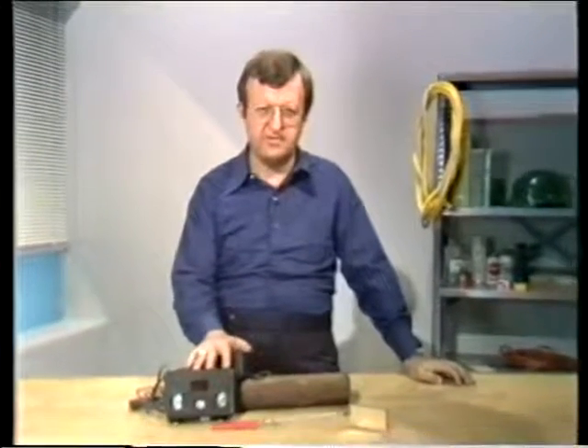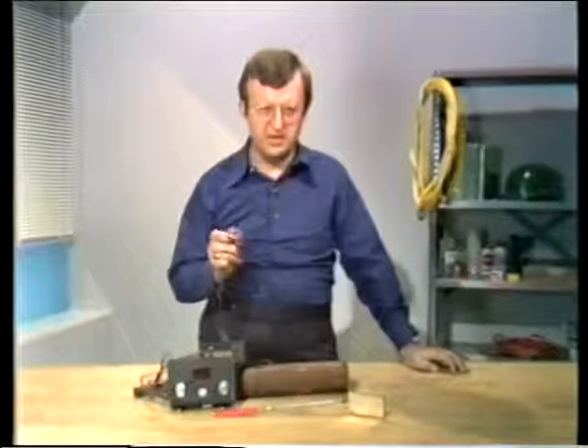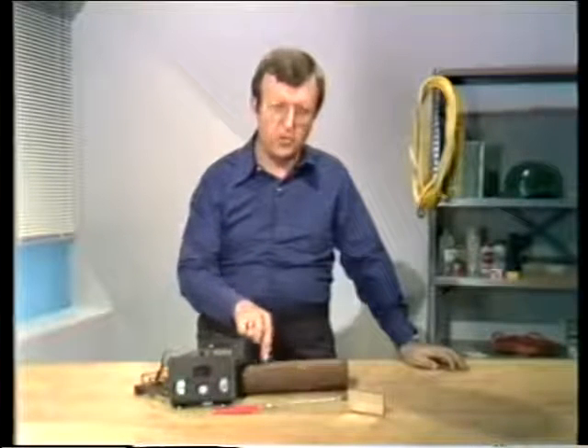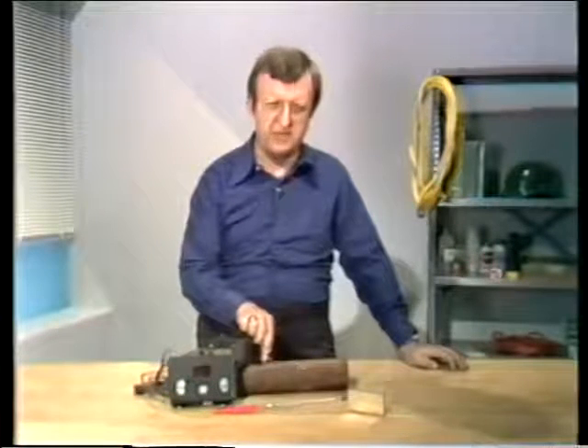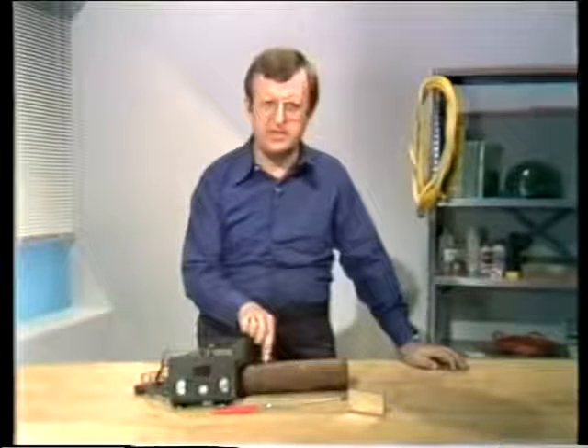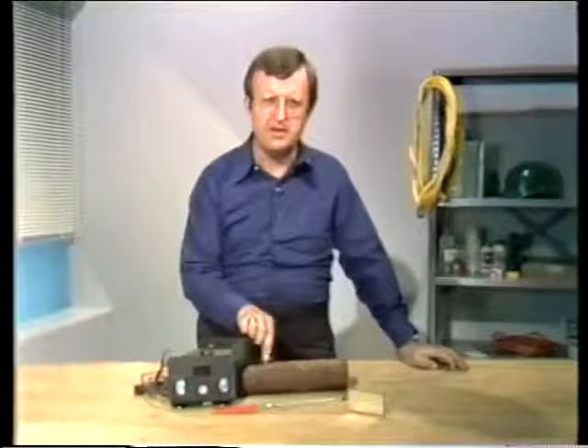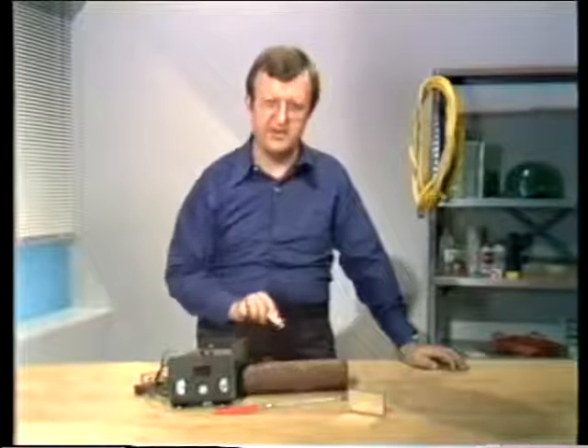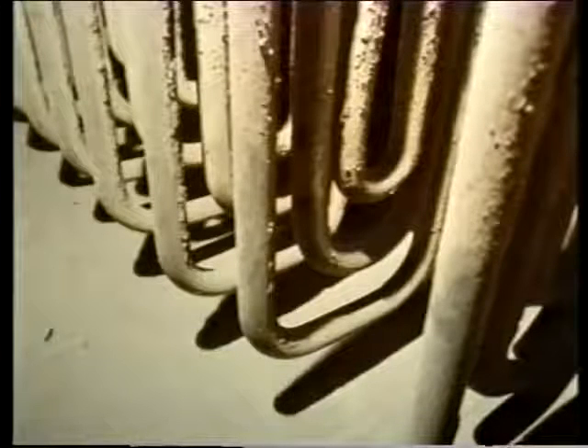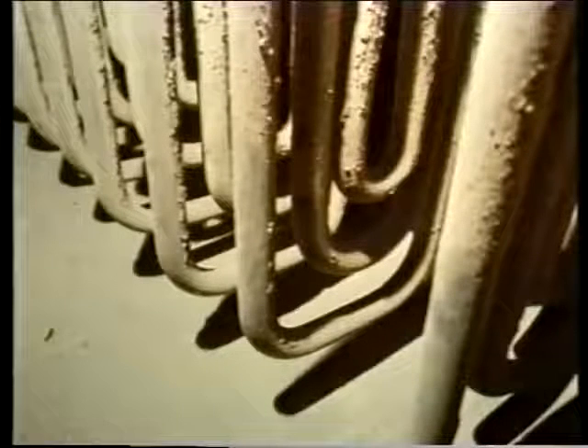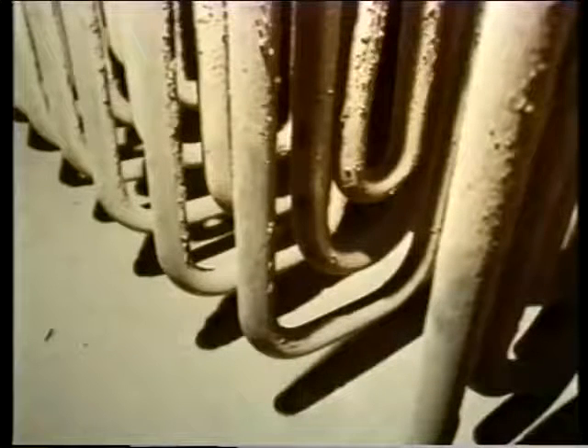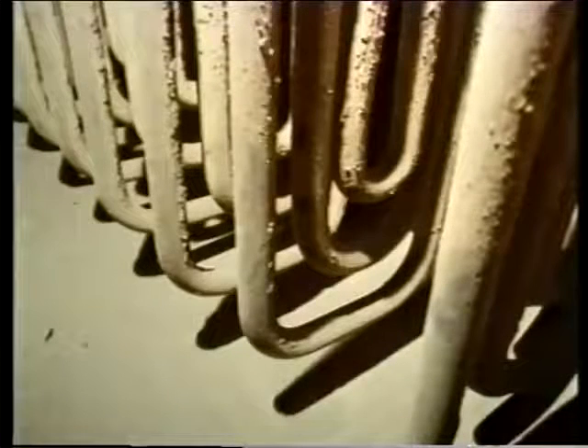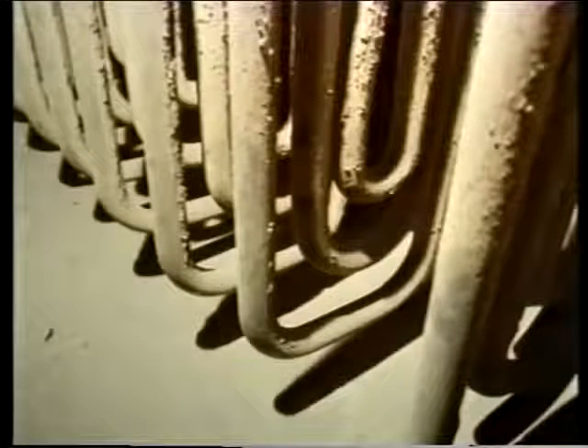must be used. Now, with this, you measure tube thickness on a worst-case basis. For example, if one section of the tube exhibits severe ash erosion, you would take measurements in that area. Wherever a tube has a bend in it, you have a possible area for erosion. Erosion takes place on the inside of the tube, but it is usually detected from the outside. Measurement from the outside of the bend should indicate whether tube thinning from erosion is occurring on the inside of